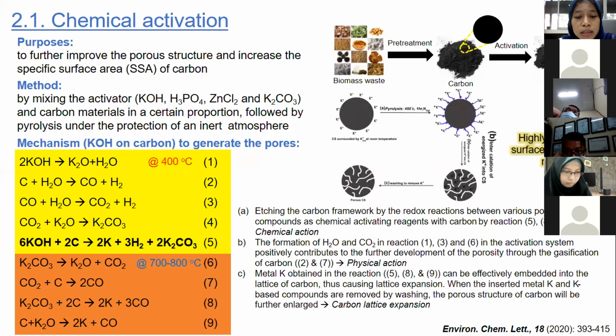Moreover, the resulting CO2 can be further reduced by carbon to form CO at high temperature. And the potassium compounds like potassium oxide and potassium carbonate also can be reduced by carbon to produce metallic K at temperature over 700 degrees Celsius. So there are three main conclusions about the activation mechanism of KOH on carbon, which have been widely accepted. The first is chemical action, physical action, and then carbon lattice expansion.